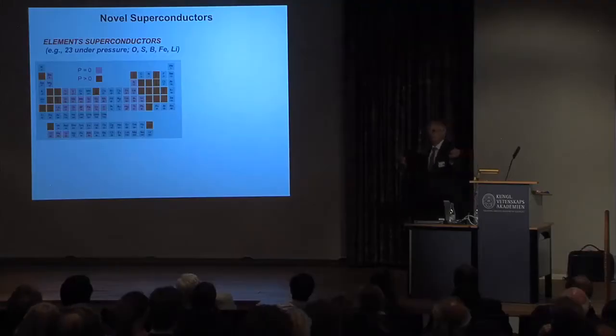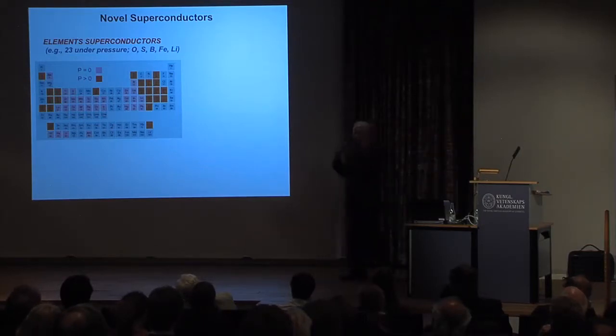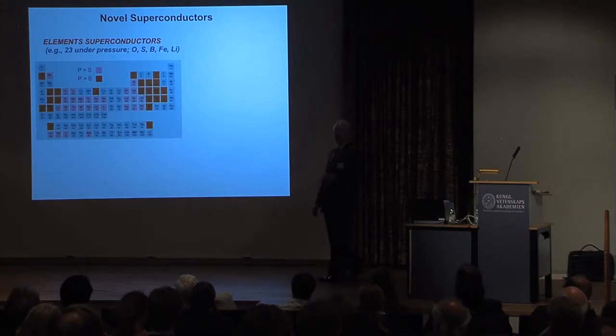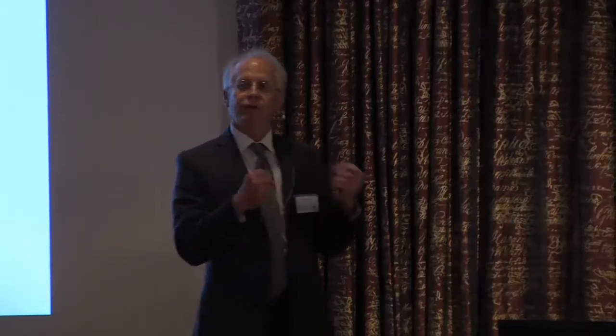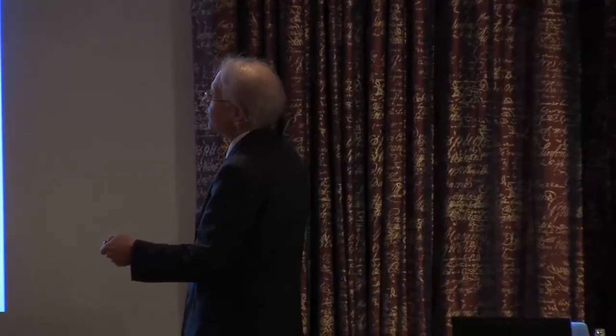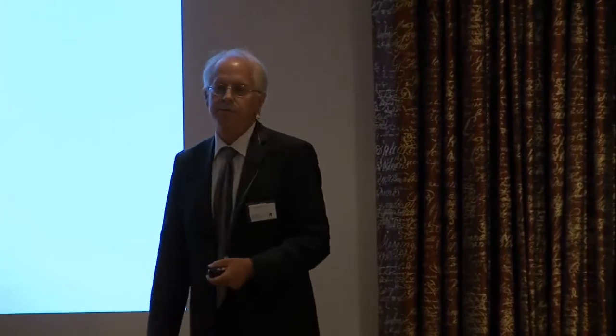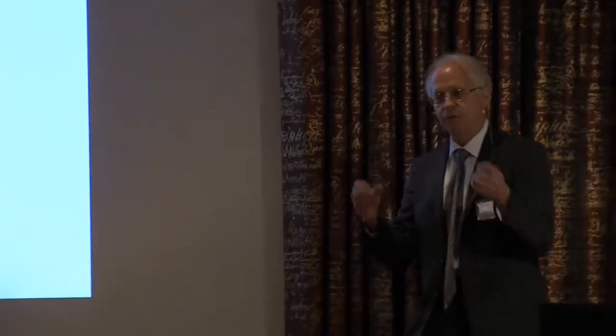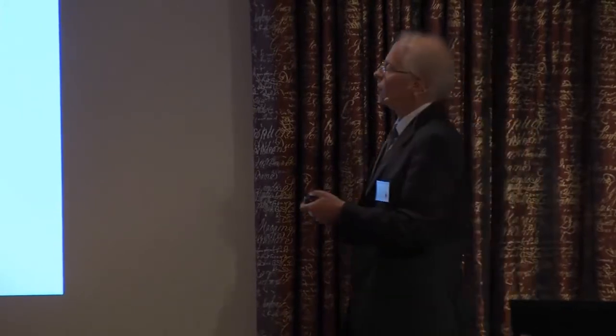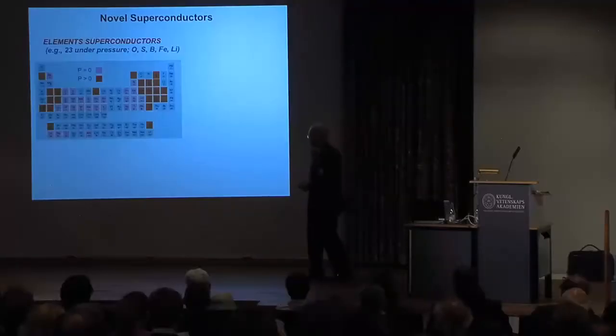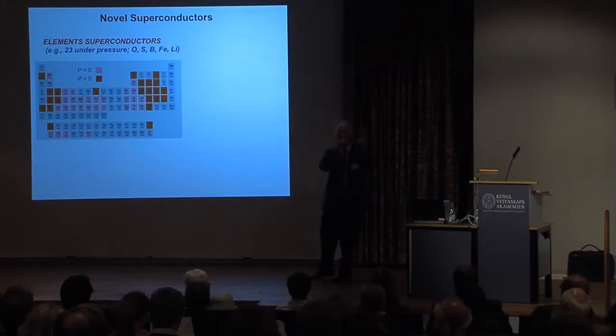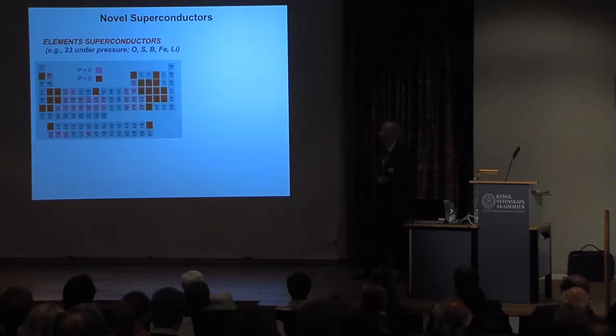Well, if there are major changes in electronic structure that lead to crystal structure changes, do we see changes at a more fundamental level? The notion of superconductors was mentioned in the previous talk, and it turns out that not only do we turn some insulators into metals, we can turn metals into insulators, we can turn insulators into superconductors. In fact, if one just looks at the elements, some 23 elements have been converted from non-superconducting states to superconducting states, some with rather high transition temperatures. And that includes oxygen, which is a gas. So here is an example of taking a gas and turning it into a superconductor at a megabar pressure.